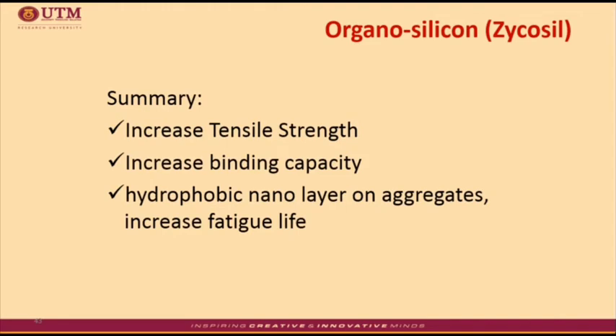Based on previous studies, the use of this material in asphalt mixture containing limestone and granite increases the tensile strength by 3% to 14% respectively compared to the control sample. Aggregate coverage with this material decreases the air voids in asphalt mixture and increases the binding capacity. And finally, this product provides a formation of hydrophobic nanolayers on aggregates, which can lead to an increase in fatigue life.